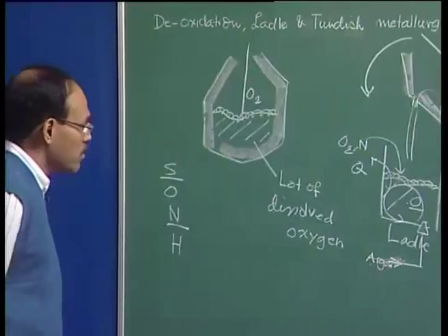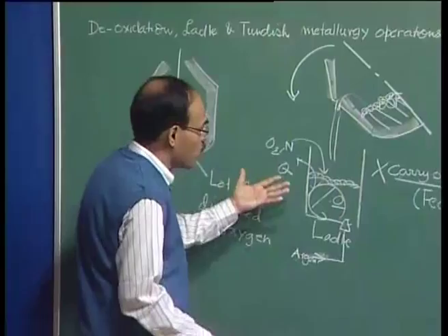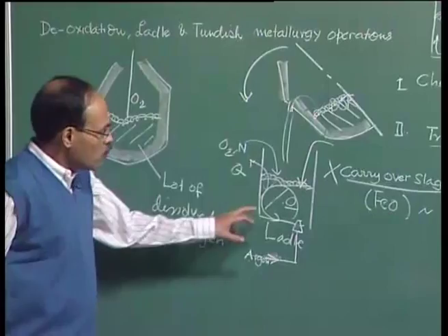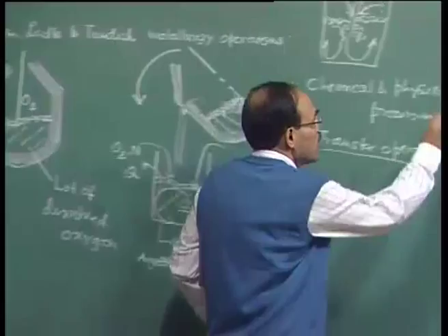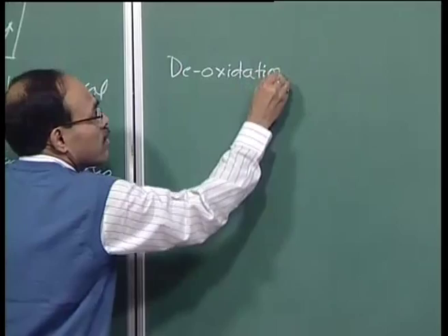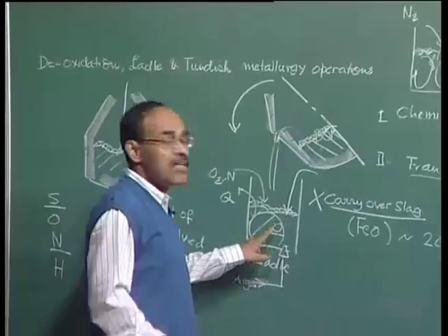We can see that before the material is completely filled, as the basic oxygen furnace is being emptied, we are going to continuously add deoxidizer elements into the steel bath. The first step, as I mentioned, is to drive out this oxygen, and this is called deoxidation of the steel bath. To deoxidize the steel bath, we basically add elements which have a very high affinity for oxygen.